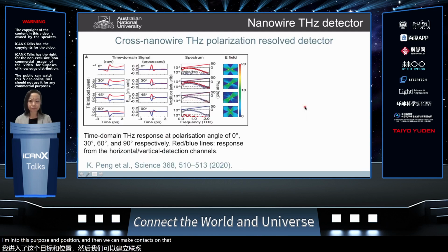And this is the result, basically showing the time domain terahertz response at different polarization angles, showing that indeed the signals received from the two channels of the nanowire detectors really have different responses to the terahertz polarization.